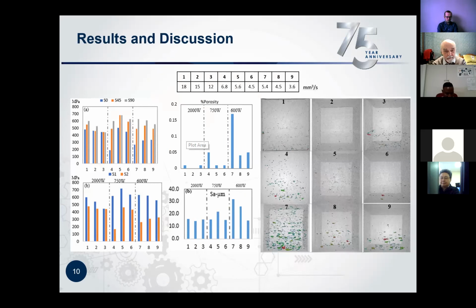So some of the results that we were able to obtain. Here I'm showing you the graphs in terms of the principal stresses. S0, S45, this just indicates the different directions. S0 is perpendicular to your scan direction, 45 is diagonal, and S90 represents along the scan direction. And then I'm also showing graphs of the porosity measurements and the images obtained from micro-CT.